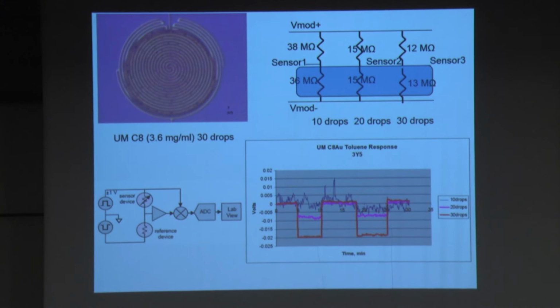Okay, here are some preliminary studies. When we jet 10, 20, 30 drops and generate perfectly matched pairs, you can see the response to toluene basically needs a certain amount of material before you start to get a nice response. If it's too thin, you get mostly noise.